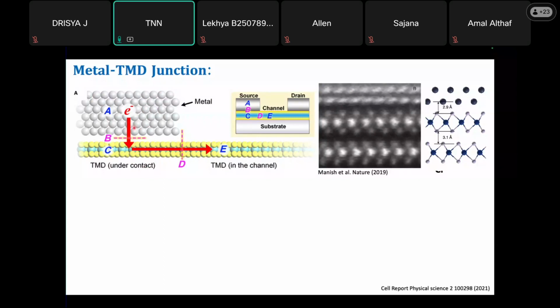One is that there can be a physical barrier between metal and semiconductor. You are depositing metal, either using thermal vapor deposition or sputtering, on top of a semiconductor. Most of the time, not always, that doesn't mean there is a covalent linkage between metal and semiconductor. So this is a transmission electron microscopic image, a cross-sectional image of a metal semiconductor junction, a gold MoS2 junction. There is a gap of approximately 3 angstrom. So this is a very ultra thin neat interface.